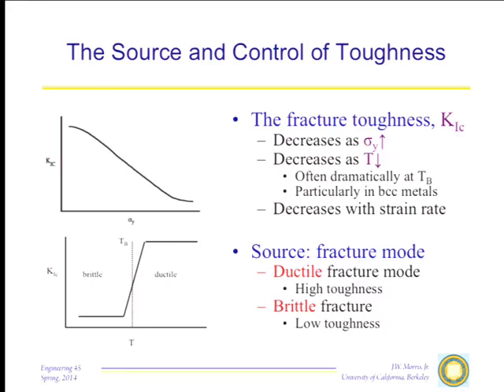It turns out in steels, in fact in all BCC metals, and some FCCs for a different reason, there is a ductile-brittle transition. For reasons I'll tell you about next time, at high temperature, these materials are ductile. There is a fairly narrow temperature range at which the fracture mode changes and they become brittle, and K1C can drop by an order of magnitude, just like that.